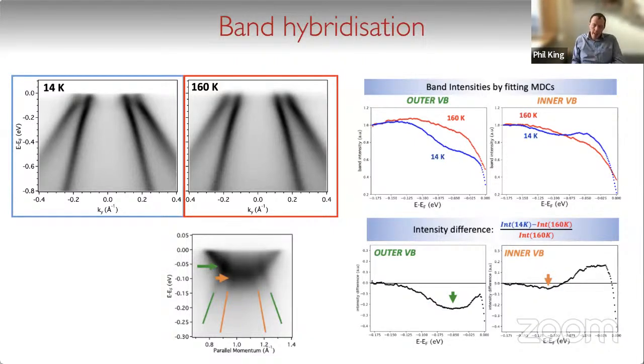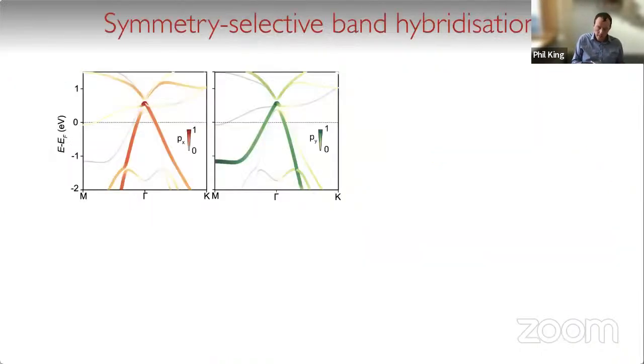But what's quite interesting in this is that this suppressed spectral weight is rather stronger for the outer crossing than the inner crossing in the system. And that's pointing to some sort of selectivity of the hybridization strength in the system between the different states we have here. So some sort of symmetry selectivity. And in fact, we can understand that on the basis of the p orbital character of these states again.